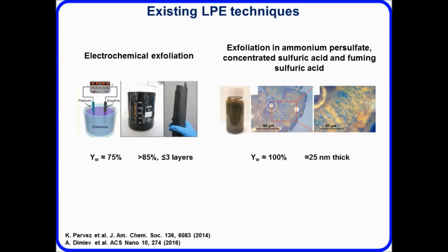The final approach I'm going to talk about is another acid-based approach. This was developed at Rice University, and it can give graphene nanoplatelets in very high yield, up to 100%, but that's graphene or graphite platelets with 25 nanometer thickness.